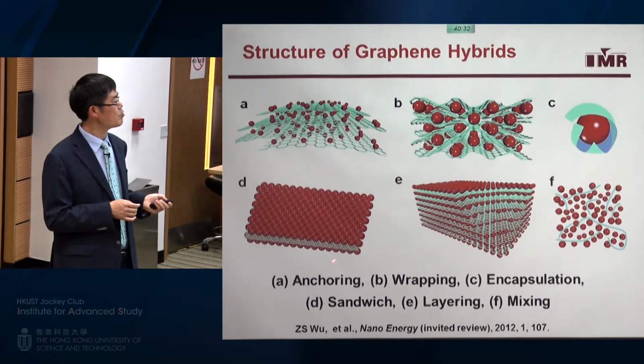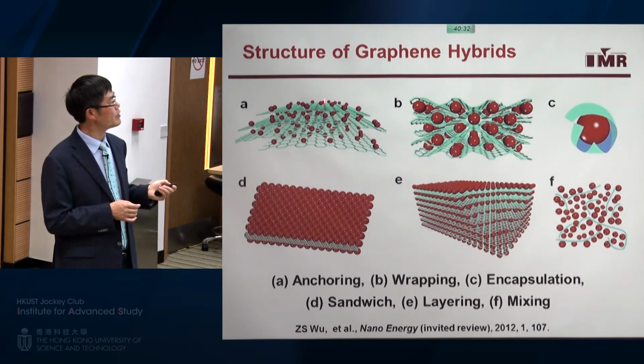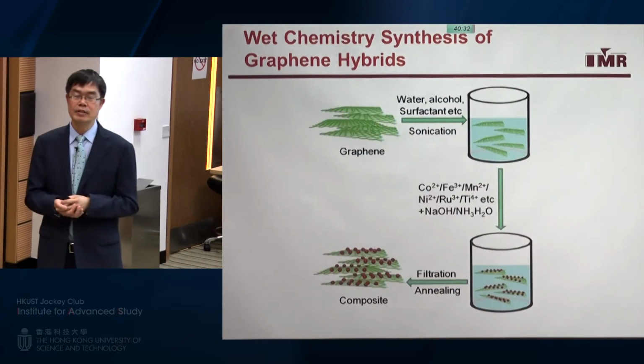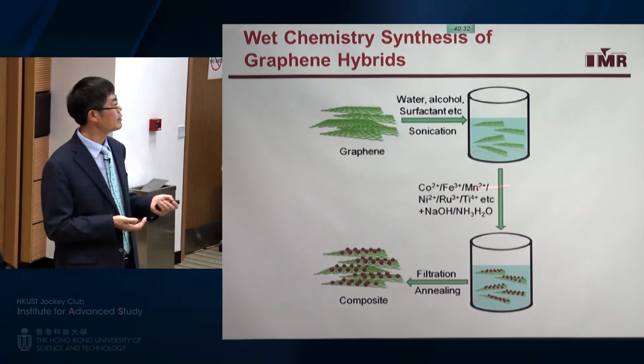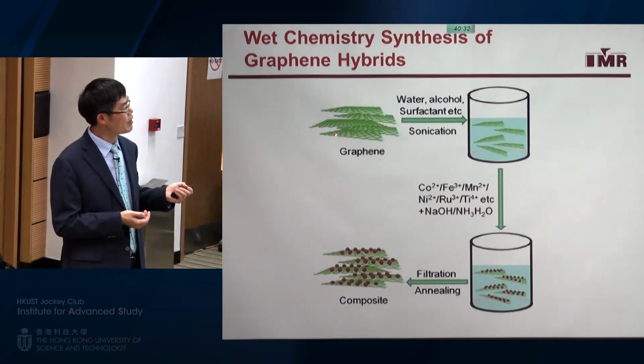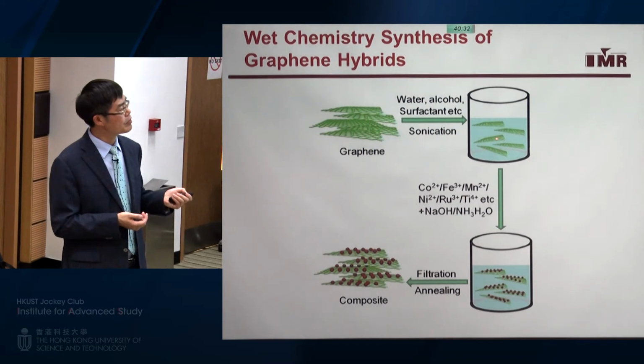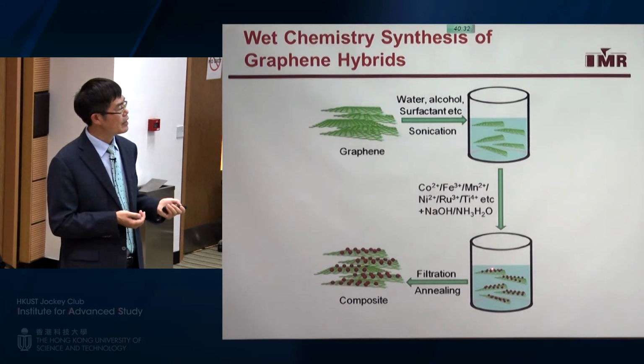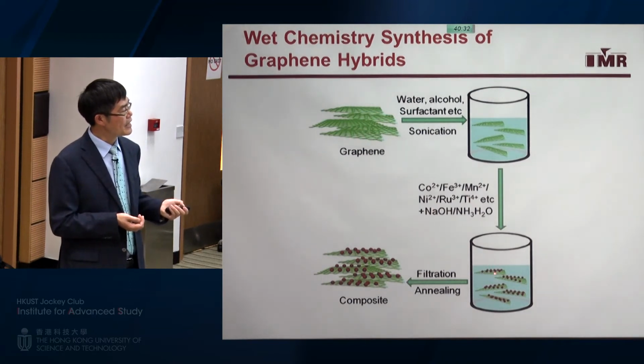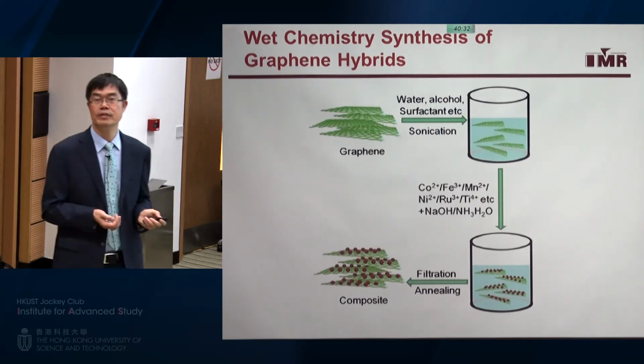So this is one of the earlier reviews for those kinds of graphene hybrid materials. They include the anchoring, the sandwich, or layered structure, or wrapping structure, and so on. And the process is quite easy, quite simple. We have graphene or graphene oxide, we put it into some solution, and then we put the oxide precursor into it, as I mentioned. So the oxide is ready to nucleate at those active sites to form this composite or hybrid material.